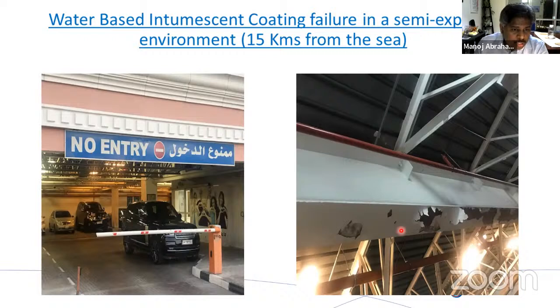Our recommendation was for a solvent-based system. The customer did not accept. They went in with this, and now this place is compromised. If there is a fire, the whole structure is going to collapse because the right coating was not used. So this is what we would say as semi-exposed. If it is fully closed and enclosed, then that's fine. But because it is semi-exposed, you're going to have a problem of humidity coming in, especially in July and August.